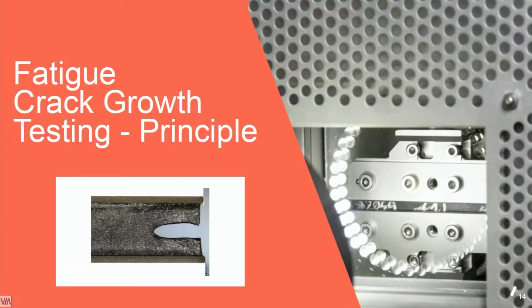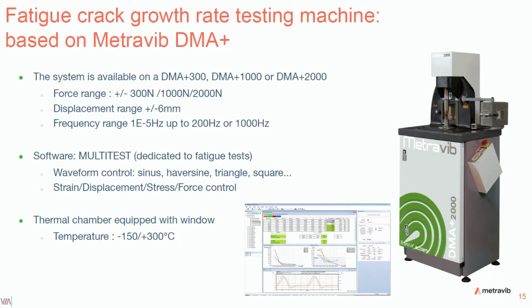So here we are talking about crack growth testing. We proposed a new product one year ago, an automated system in order to characterize crack growth rates. This system is available only on the DMA Plus series, that is to say DMA Plus 300, 1000 and 2000, because we use specific software for that named Multitest, instead of DYNATEST, which is in charge of simple DMA characterization. With Multitest, we have perfect control of the waveform of the signal: sinus, haversine, which is a type of signal we can use in the tire industry, triangle, square, etc. We can control strain, displacement, stress, and force.